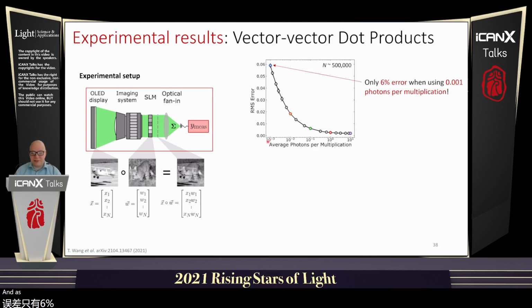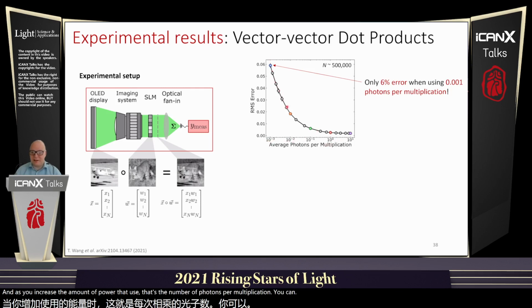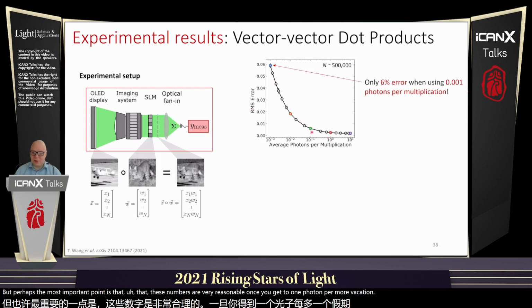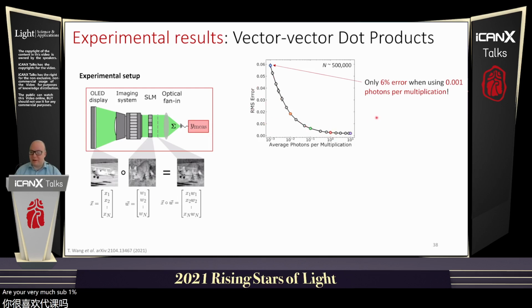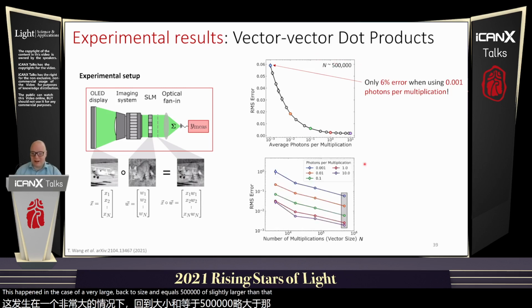And as you increase the amount of power that you use, that's the number of photons per multiplication, you can see that the error decreases as you would expect. But perhaps the most important point is that these numbers are very reasonable. Once you get to 1 photon per multiplication, you're very much sub 1% error. This happened in the case of a very large vector size, n equals 500,000 or slightly larger than that. And if you have a smaller vector size, then the error increases, which is something that you would expect.